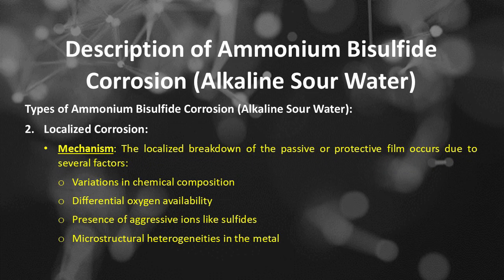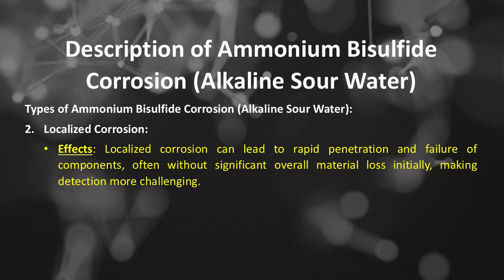The mechanism of localized corrosion. The localized breakdown of the passive or protective film occurs due to several factors, including variations in chemical composition, differential oxygen availability, presence of aggressive ions like sulfides, and microstructural heterogeneities in the metal. The effects of localized corrosion.